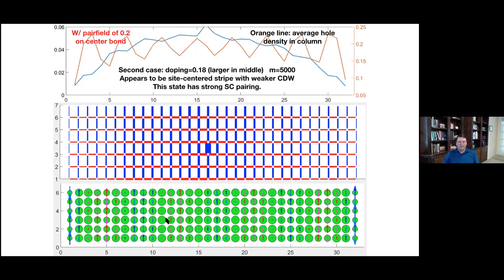It looks a bit like they're site-centered stripes, so the domain walls look like they're on sites. We don't think that's too significant. And the spin structure of the stripe is a little bit more apparent than the density structure of the stripe. Okay, so that's a second state.